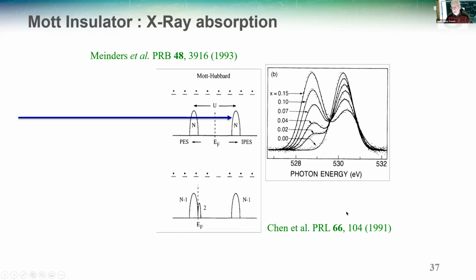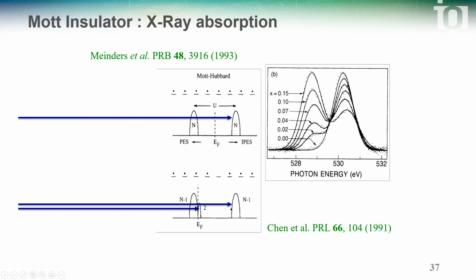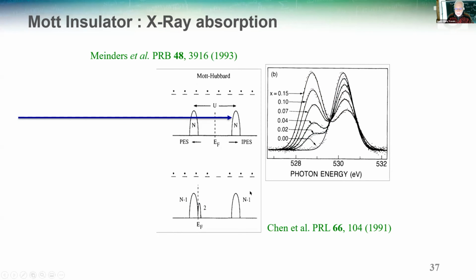If you take a very high energy photon, like 530 eV here, and you send it, then you see that, let me do this more slowly. Sorry, I went ahead of myself. Now here you see that you get a single peak. If you're at zero doping in the Mott insulator, you get a single peak. Now, if I dope a little bit, in other words, I remove an electron, I have n-1 states now for removing electrons, n-1 states for adding electrons, and the two missing states correspond to putting an up or down electron on that site. Then that's near the Fermi level.